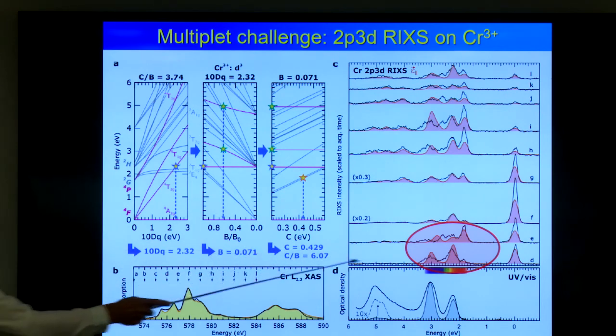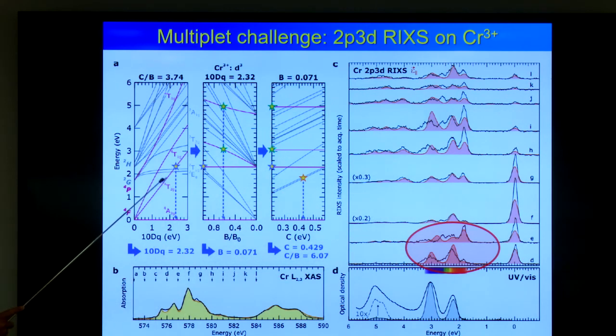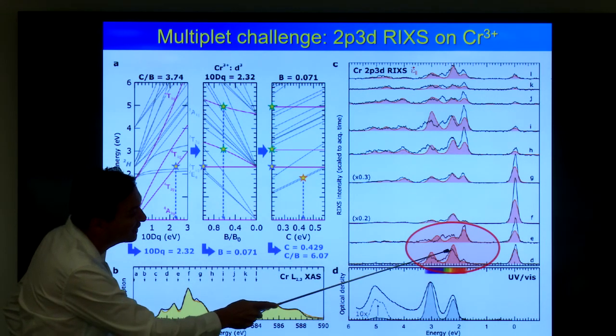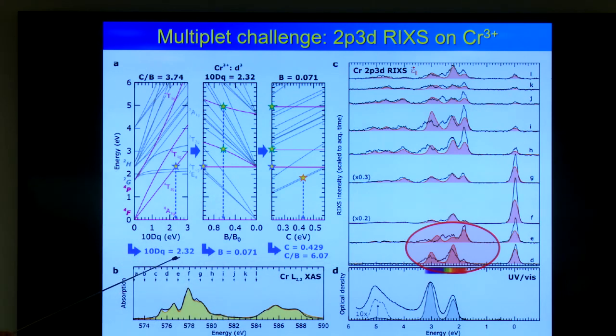And now you can analyze these RIXS spectra from semi-empirical calculations, and then you can see that this peak is the first peak in optics. That's the spin allowed transition, this one. And spin allowed transitions do not change if you change the Slater integral, so the Racah parameters. So this is Racah parameter B and Racah parameter C, so the electron-electron interactions. The energy of that peak is completely insensitive to any of the electron-electron interactions. So that means you can optimize the crystal field splitting directly from the position of that peak in optics. So now you can do it at least in 2 digits.